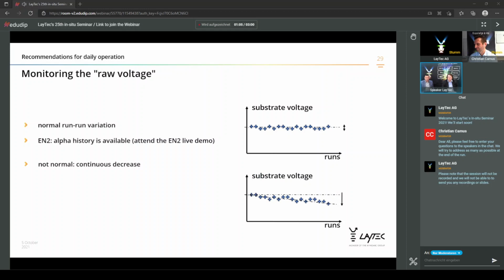So what we see, if, for example, the viewport is coated, what Heiko already explained, is normal behavior of the tool, even when the viewport is purged properly. After a certain time, you will see in the substrate voltage a continuous decrease of the intensity. So the first check you should do is: are all wavelengths affected with the same ratio? It might occur that the shorter wavelength is affected more strongly. This leads to the assumption that window coating is happening.